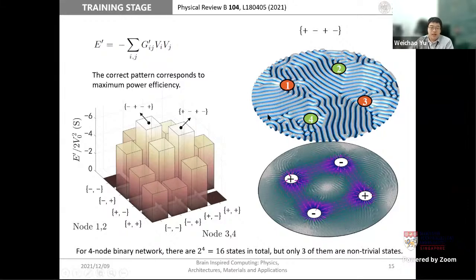And then we can obtain the conductance matrix according to the configuration and calculate the energy function according to all 16 combinations of the inputs. It's clearly seen that the energy function reaches a minimum for 2 states, the state minus plus minus plus, and the state plus minus plus minus, which means the ground state of this network is modified after training, and the texture has successfully memorized the pattern we fed to it.